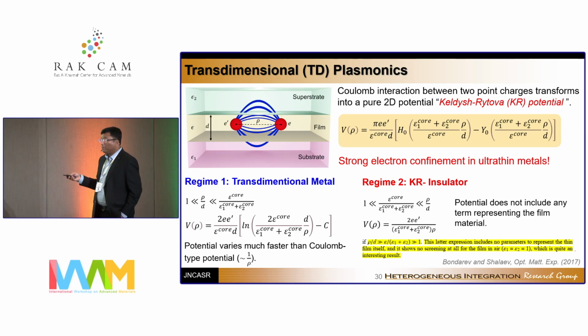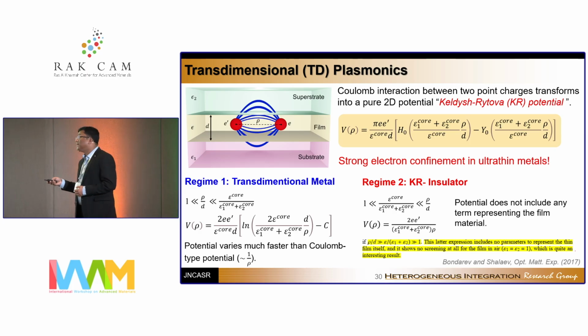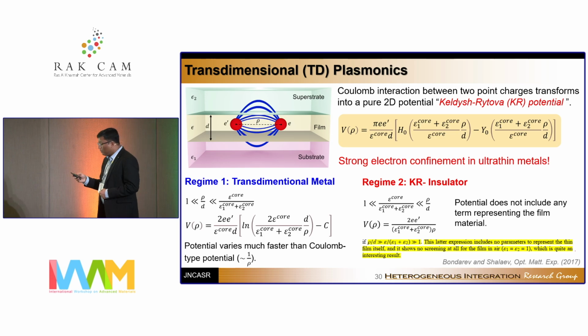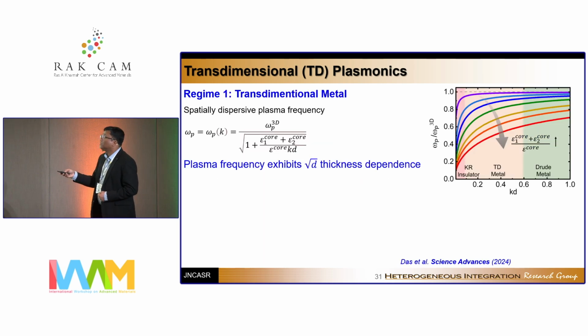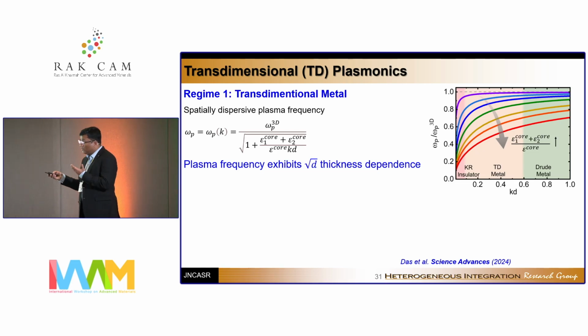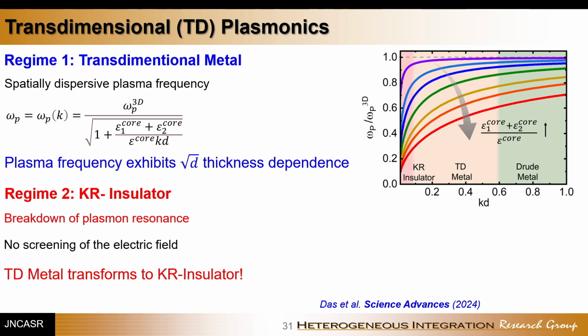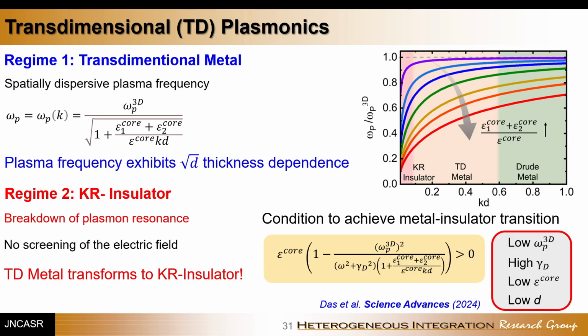One is the transdimensional metal regime, where the material is still a metal, but with some changes in the dielectric nature. More specifically, the plasma frequency now has a root d dependence on the thickness of the material. So plasma frequency is now a function of the thickness, d. But the second regime is basically the KR insulating regime, the Keldysh-Rytova insulator regime, where plasmon resonance basically breaks down. In other words, there is no screening for the material. The material cannot screen any electric field in this case. And that has a very stringent requirement. Of course, if you can hit the experimental condition, then one should be able to see it.